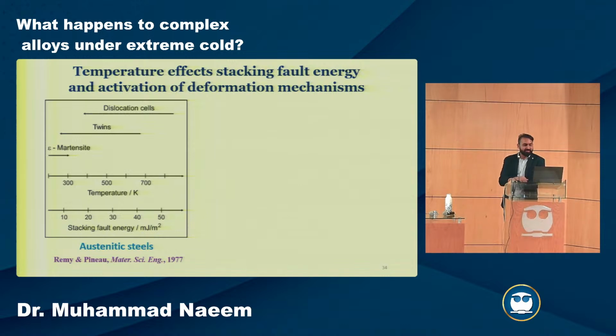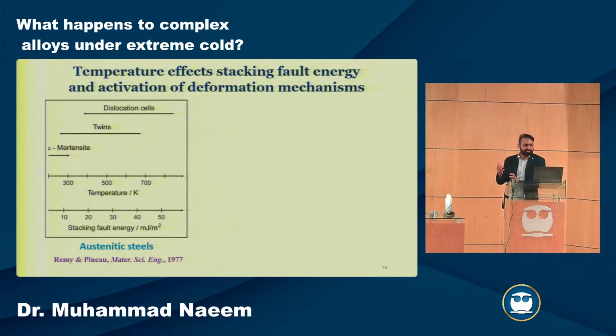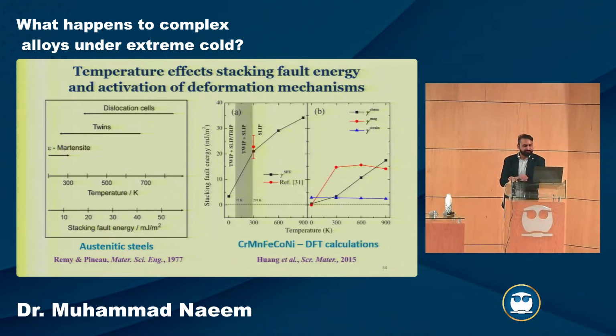If you have stacking fault energy up to, say, 40 millijoule per meter square, it is mainly dislocation slip. But if you go below that, now you can activate deformation twinning. And if you go further down, then you can have martensitic transformation, and it can depend on temperature as well. So you can control that. You can have a different behavior depending on temperature.